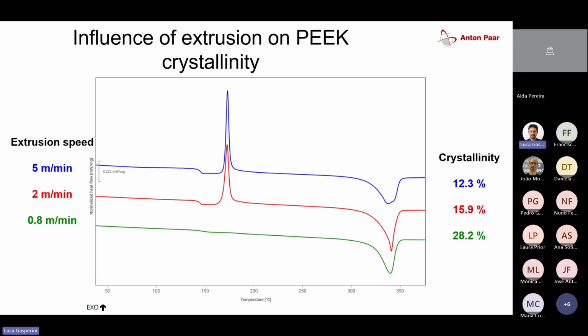And that shows us that the drawing speed is an important factor in giving the material the final characteristics of crystallinity. Very similarly, as we've seen with the PET, the higher the initial crystallinity, the lower the amorphous content, and the less pronounced the glass transition. Because the amorphous part of the polymer is responsible for the glass transition, and in a semi-crystalline product, it's the crystalline part that is responsible for the crystallization and melting processes.